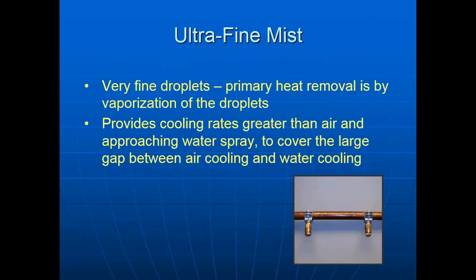We have incorporated in some of our units an ultrafine mist system. The ultrafine mist uses nozzles that create very fine droplets, and the primary heat removal is actually the vaporization of the droplets. If you calculate the temperature of the mist, you're going, it shouldn't be able to do that. But what's happening is you're actually flashing off the droplets and creating cooling rates approaching that of a traditional water spray. We did that to span the gap from the maximum air cooling and the minimum water cooling, because there's a big gap between those two, and that can be partially filled with an ultrafine mist subsystem.